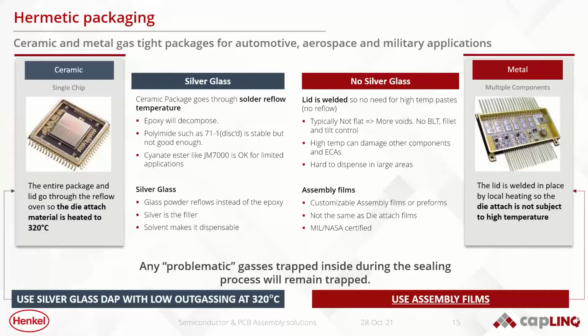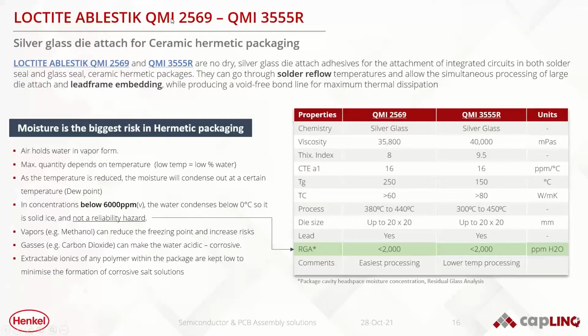So I don't want to spend too much time on it, except to say that the technology for these materials is really in the assembly films that you see down here, and also the silver glass die attach paste that is used inside of hermetic packages. The QMI2569 and the QMI3555R are older than I am, almost, but these materials have been used reliably for hermetic packages for years. The QMI2569 is the easiest for processing, whereas the 3555R is used for lower processing temperatures, and in these cases, lower means 300 degrees Celsius.